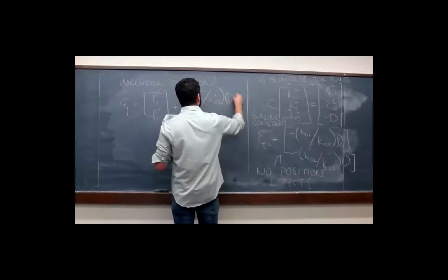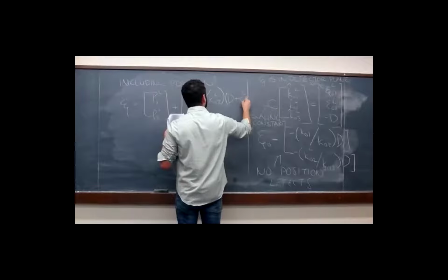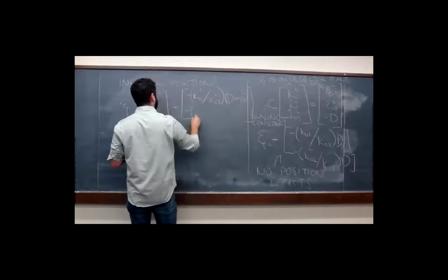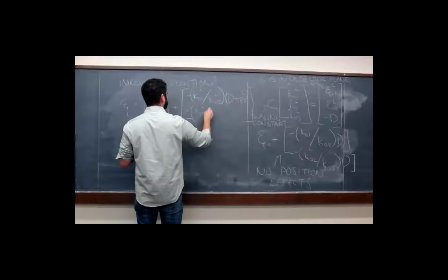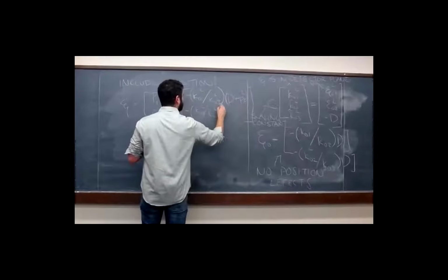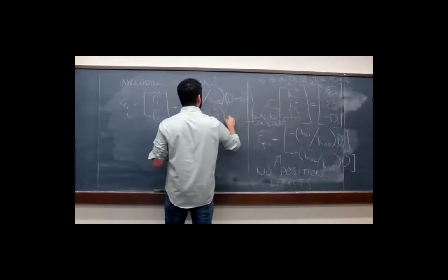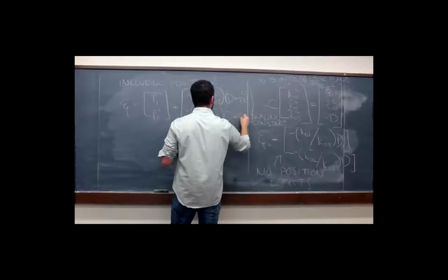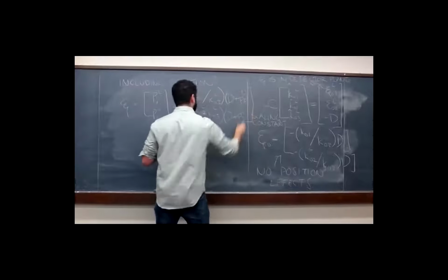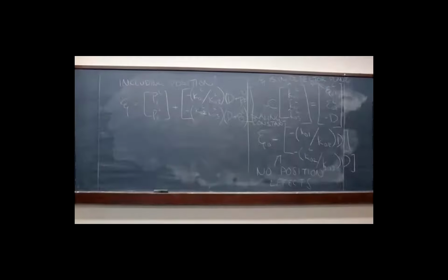And that the position along the beam direction ends up just being a scaling here and added to our distance. So this equation can be quite informative for understanding where diffracted intensity can show up on the detector and what becomes dominant.